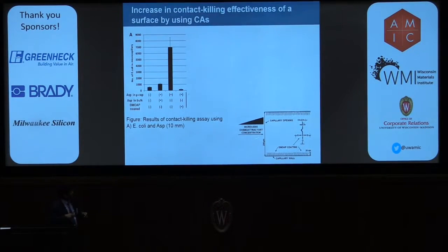Now, coming to the case where we established the concentration gradient outside the capillary. In that case, we see that we have attracted a lot of bacteria, around 8 to 10-fold over our controls, inside the microcapillary. And to this system, when we add the contact-killing antimicrobial, we show that we have reduced the number of bacteria. So we are, in essence, killing all the bacteria that we attracted inside the microcapillary.